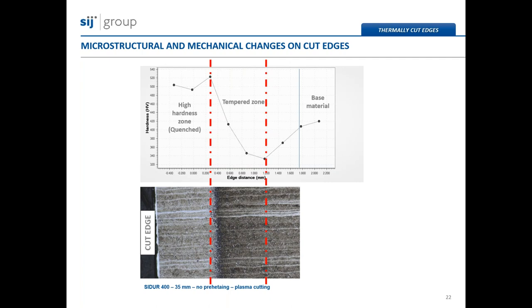So we recommend removing the white zone on those parts of the cut edges where bending will be done additionally. This white zone, which is, as I said, only 0.2 millimeter wide with high hardness and low impact toughness, is much more prone to cracking and therefore can act as a crack initiator.